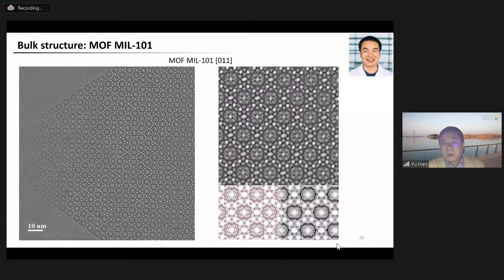Well, following the same logic, we started with imaging the bulk structure to confirm the imaging condition is safe. And as I said, MIL-101 has a very complicated structure, but still our image shows perfect matching with the projected structure model. This is our image, this is the structure model, and this is the simulated potential map. So all the main structure features, like these mesoporous cages, the surrounding smaller channels and clusters, even the metal clusters, can be clearly identified in the image.